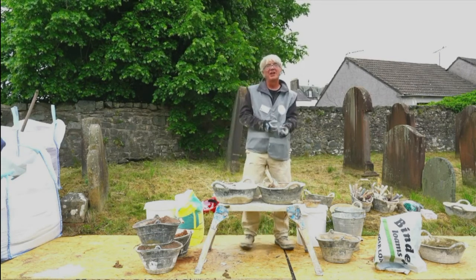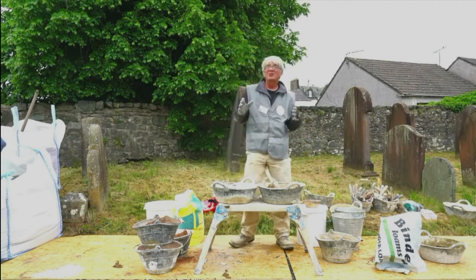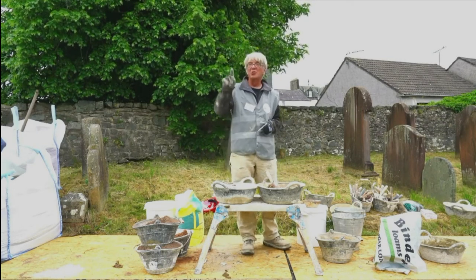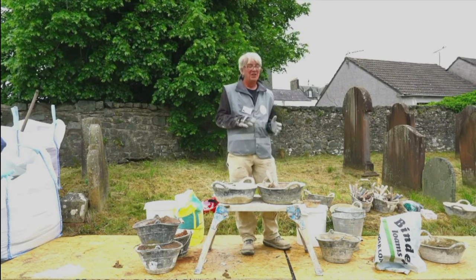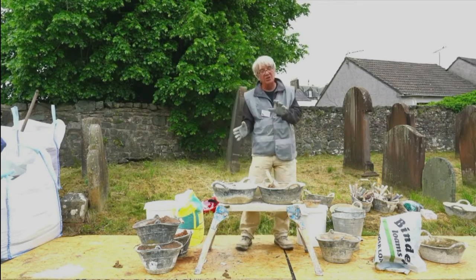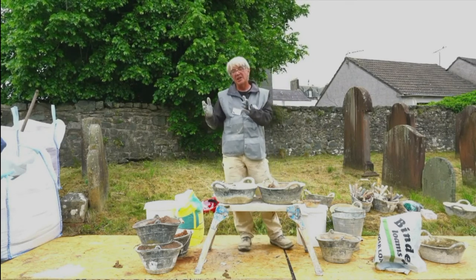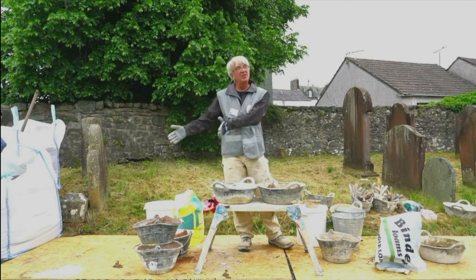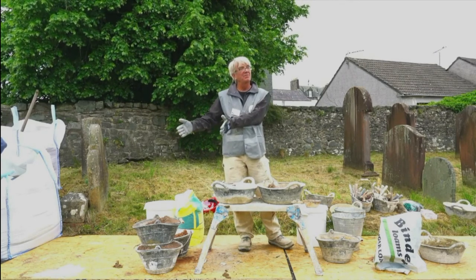You've done all this and then suddenly it looks like it's full of bullet holes. So someone's coming with an air rifle. That's what late slaking looks like. It lifts the surface off. And there's always a white dot at the bottom of it. So again, we shouldn't confuse. A lot of the things we say that are bad about lime, that's NHL that gives those bad things because of its nature.